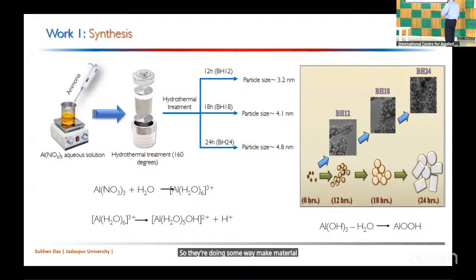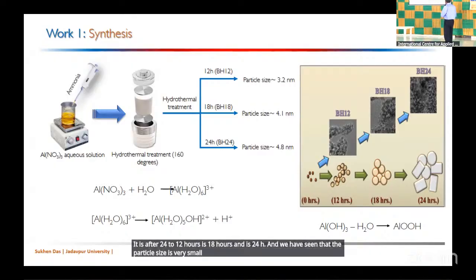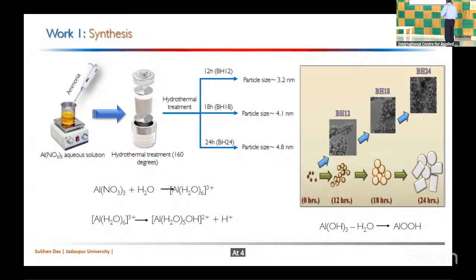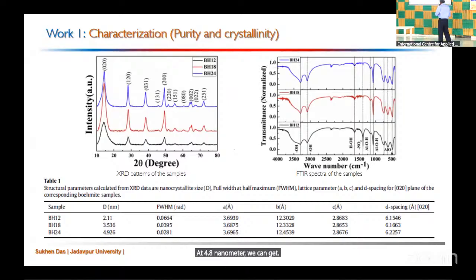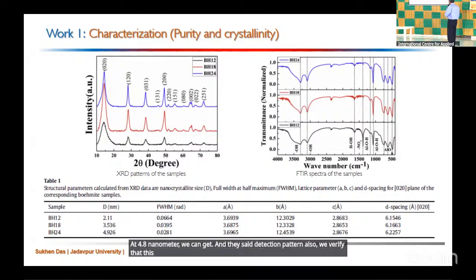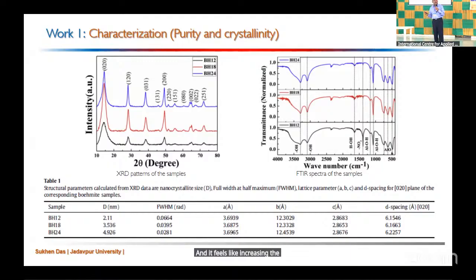It is after 12 hours, 18 hours, and 24 hours. And we have seen that the particle size is very small: 3.2 nanometer, 4.1 nanometer, and 4.8 nanometer we can get. And from the X-ray diffraction pattern also we verify this. It is for the 12 hours is the black one, and for the 24 hours is the blue one. Because as the time increases, the crystal size increases. So as the crystal size increases, the surface area of the material is decreased.